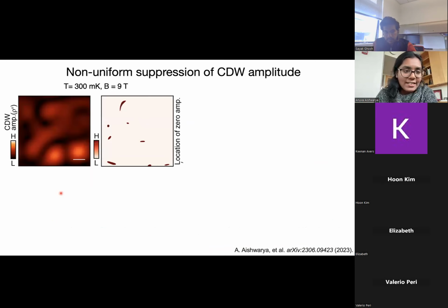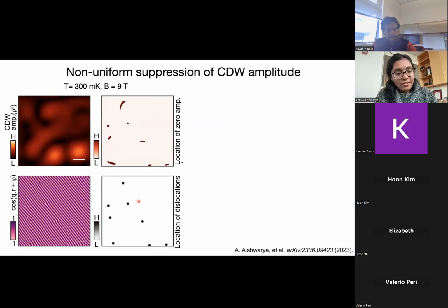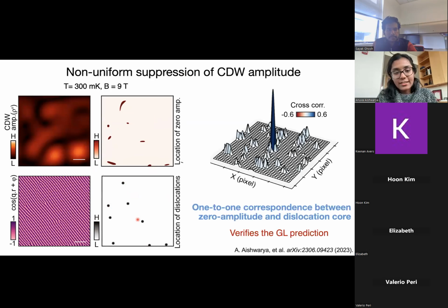What is more interesting is that if we map out regions of 0 amplitude, which is shown by this map here, and then find out the positions of the cores of these dislocations and perform a cross correlation of these two maps, we can see that there is a one-to-one correspondence between the dislocation core and the regions of 0 amplitude. What this indicates is that the way the CDW is getting suppressed is through the generation of these dislocations. And when the dislocations become enough in number, they kill long-range order. And this verifies the Ginzburg-Landau prediction.